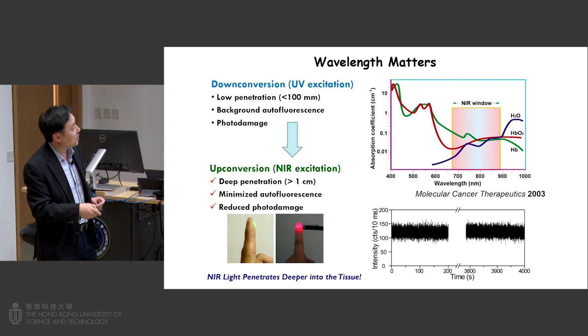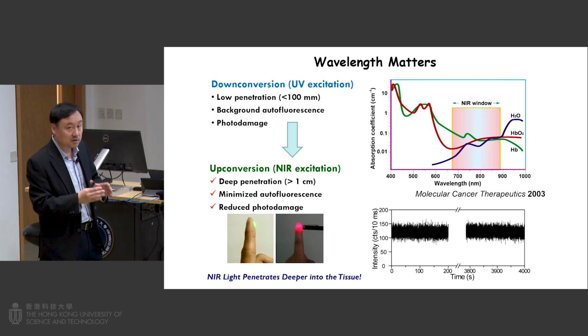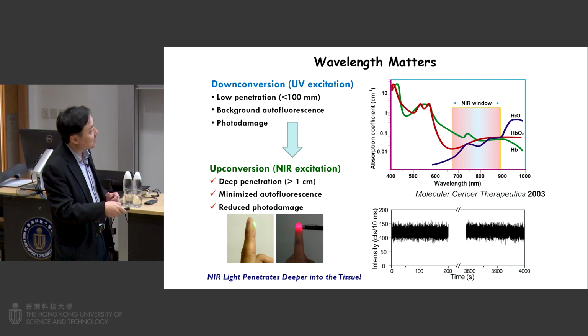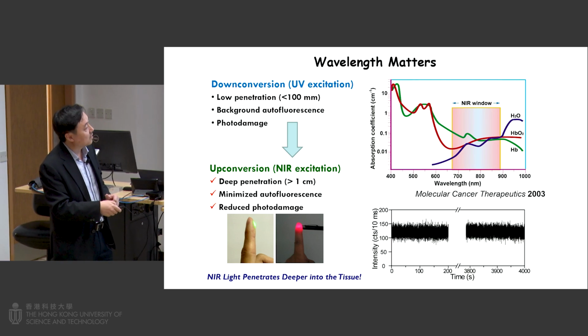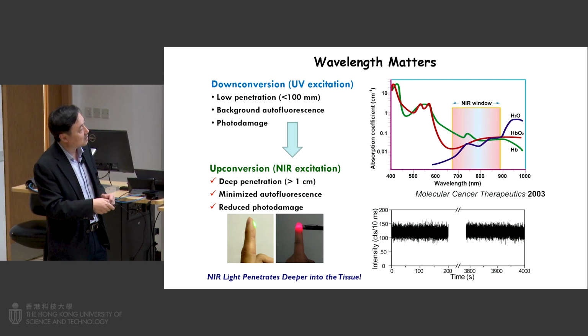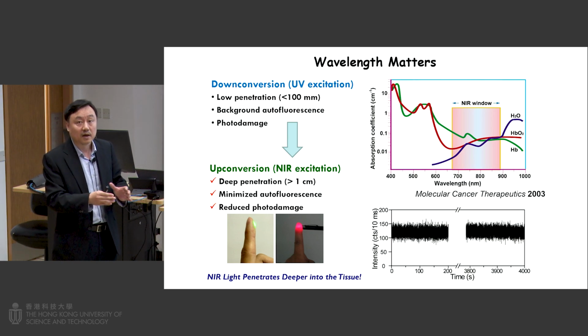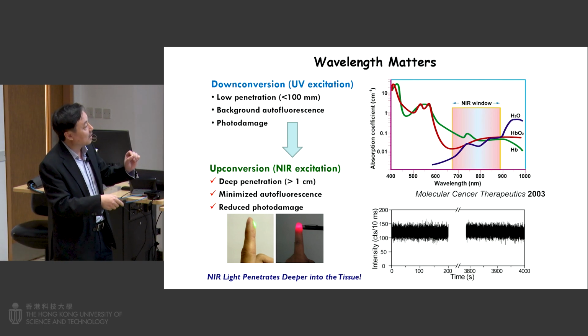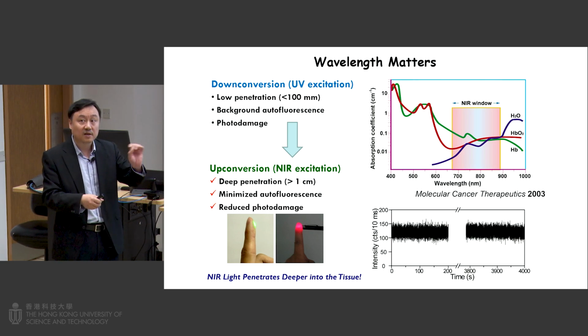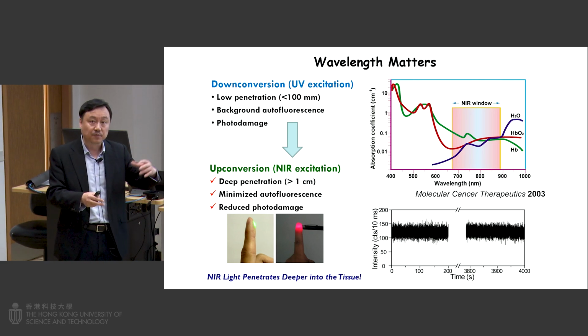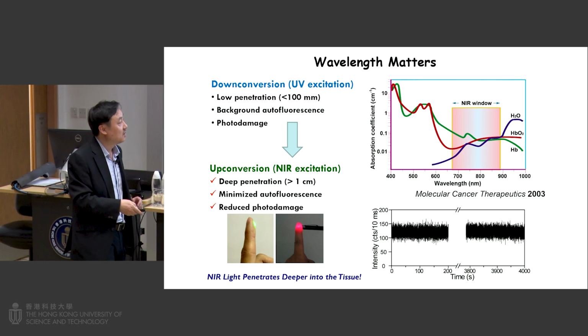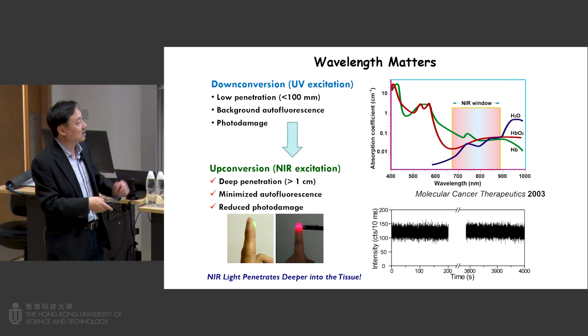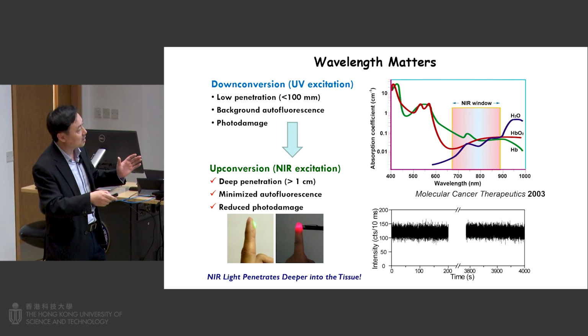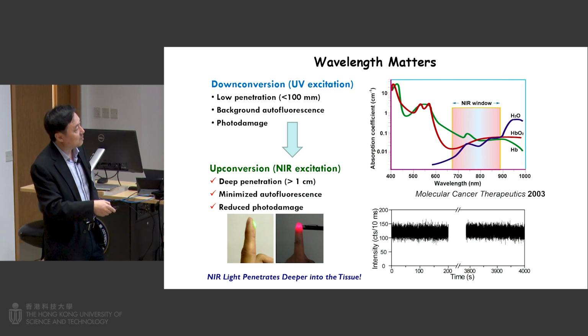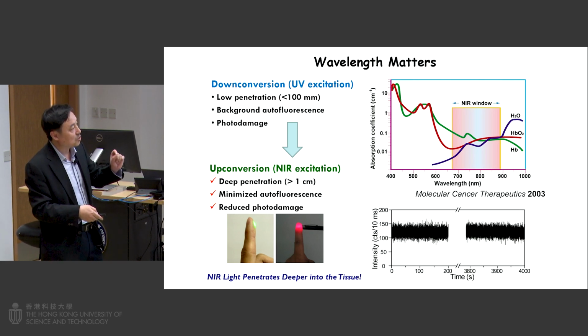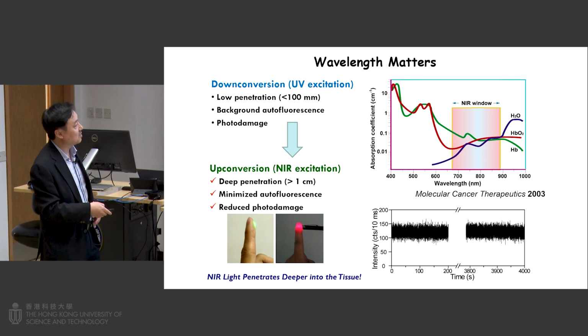Also, these lanthanide-doped particles have very good photostability. You can see here time-dependent photophysics studies showing that the particle luminescence is very consistent. Intensity remains essentially unaltered because within these particles you have many lanthanide emitters. Unlike organic dyes with bleaching, quantum dots have blinking problems. So lanthanide-doped particles give very consistent emission over a very long time. This gives the capability for in situ tracking. I will give you some examples using this technique.